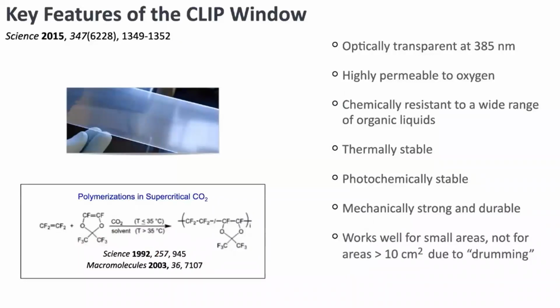Now, what kind of window does this? It's typically a fluorinated material. And we began studying fluoropolymers a long time ago. You can make an amorphous form of Teflon that is optically transparent at 385 nanometers, is highly permeable to oxygen, is very chemically resistant, thermally stable, photochemically stable, and mechanically strong because there's lots of forces on the part.